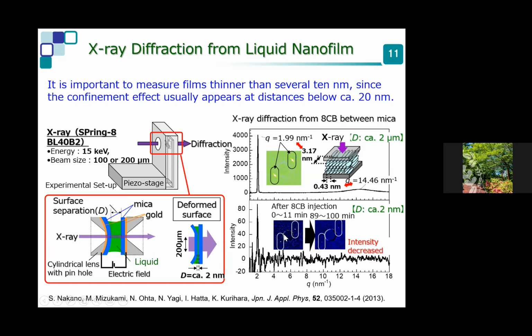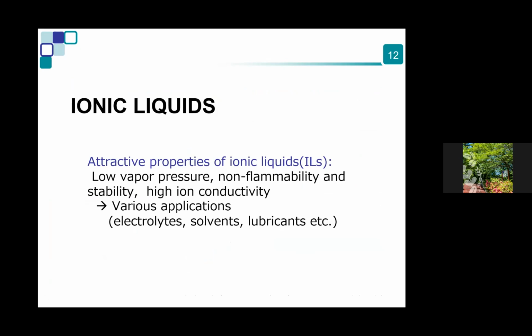Anyway, this is the signal corresponding to the longer molecular length. And also at 2 micrometers, we have seen a short length corresponding to 0.43 nanometers, a very small peak. But this peak is very clear for the 2 nanometer thickness film. Then we wanted to regulate the distance better. Now we do it with a feedback system, and the most studied system we have done so far is ionic liquid.